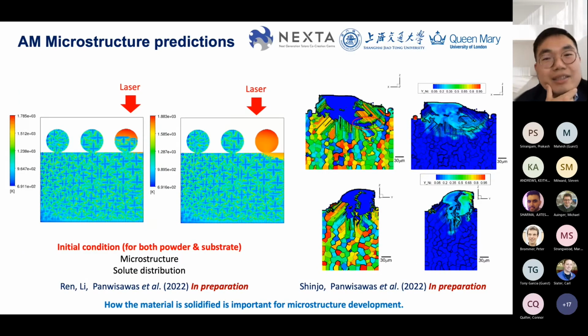So in order to actually understand the role, not just of the thermochemical fluid, but also link this one to the solute field, which actually happens in the solid state of the material, we are now investigating the role of the interaction of the laser and the powder as a function of the chemistry, and then we can elucidate some phenomena like solute trapping or rapid solidification that leads to non-equilibrium microstructure. This work is quite important, because in order to understand how materials solidify, it's important for microstructure and property scatter in the process. And for example, if we use in-situ alloying, how can we understand what is the solidification pathway for that system? And that's what we are developing a mathematical framework to do.